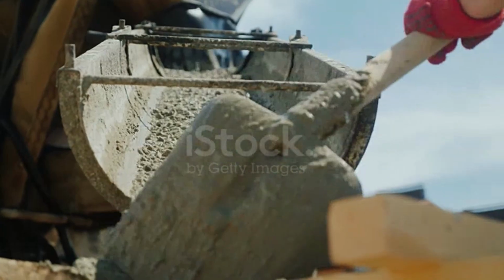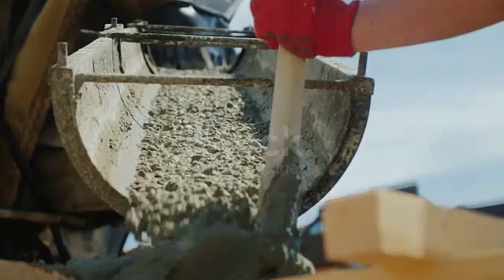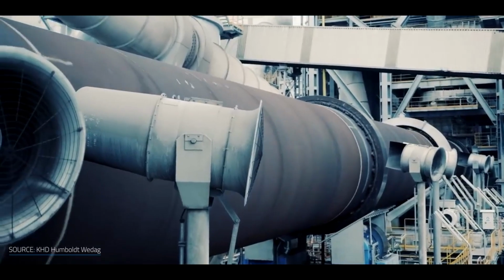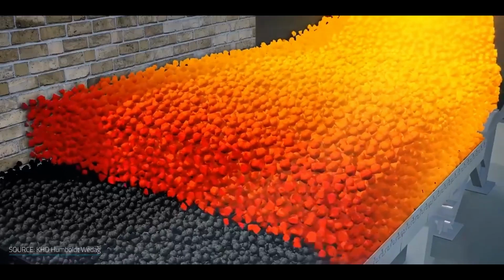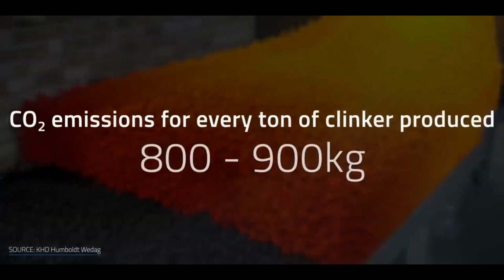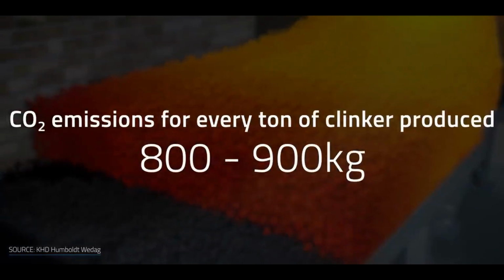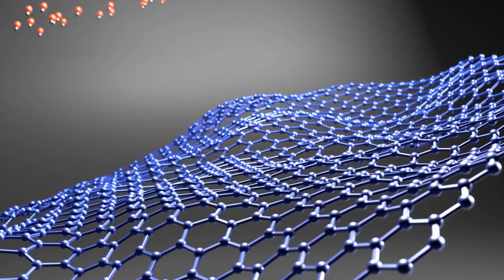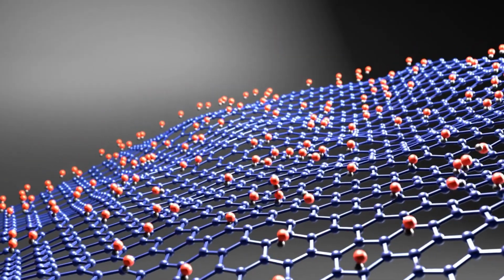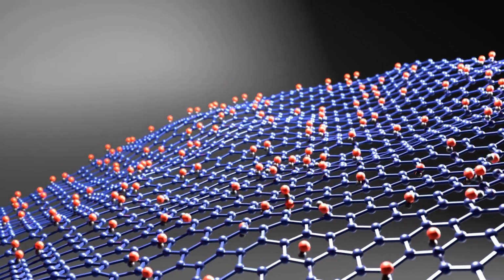In the cement production roadmap, the main focus of carbon emissions is associated with the rotary cement kilns, where the raw meal is burnt and calcined into something called clinker, which is used as the binder of cement. In this process, huge amounts of electricity are spent, and for every ton of clinker produced, we're talking about 800 to 900 kilograms of CO2 per ton. So, first, graphene is tackling the final grinding step, where graphene can improve the efficiency of the cement grinding process.